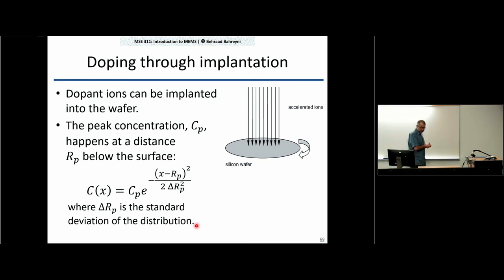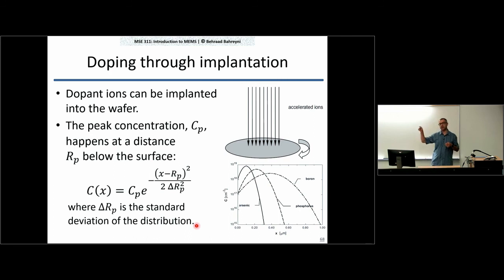The concentration profile is like a Gaussian, where the peak is below the surface. Remember, we need to slow down these ions that are coming in. So they go in, and then you have a maximum concentration somewhere below the surface. The higher the energy, the deeper that peak will be, the farther away from the surface.